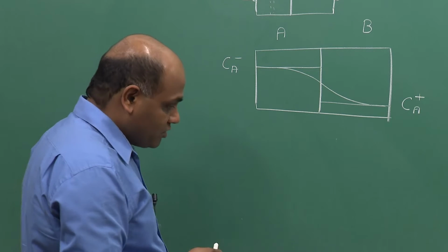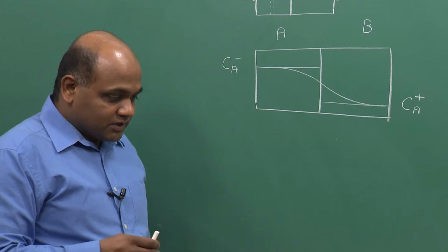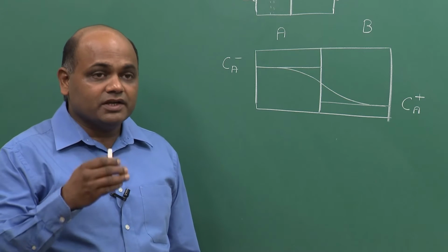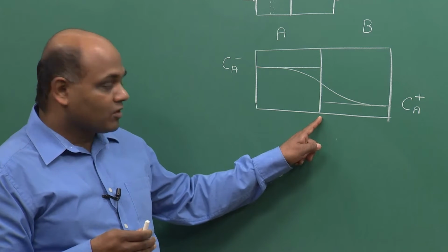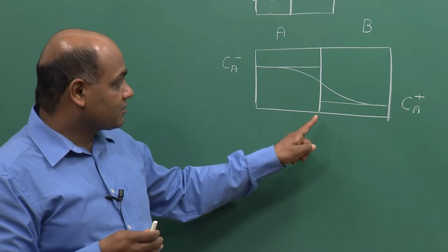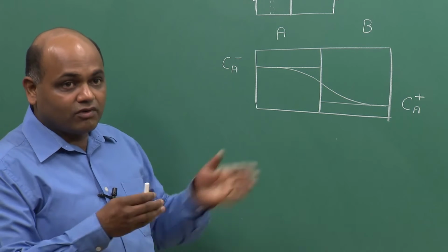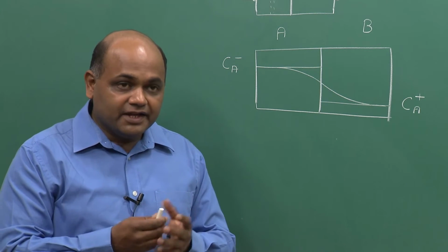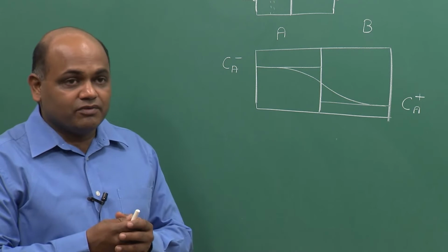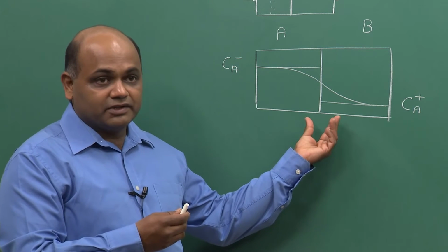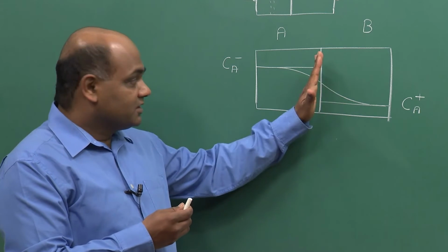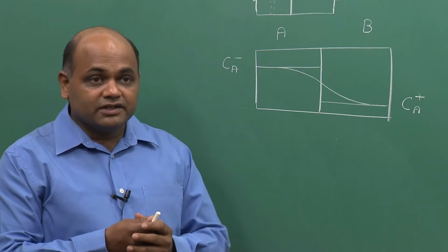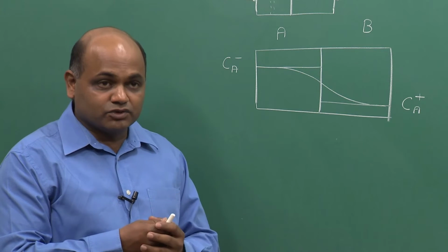Okay. So, the first issue here is how do we locate this initial contact plane. Initial contact plane is the plane of contact before the diffusion started. Ideally, if there is a good diffusion bonding that has occurred between the two alloy blocks, this plane would not be physically distinguishable in the diffusion zone.